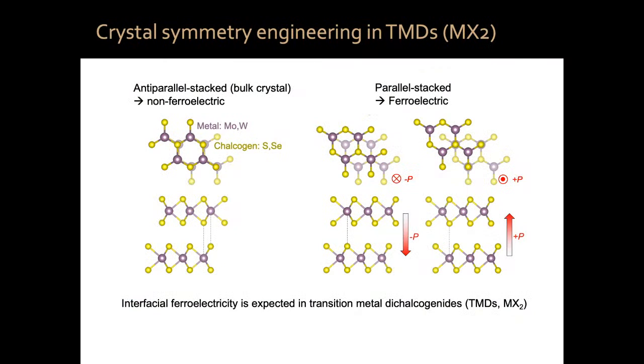only thing that we needed was to have this bipartite lattice. So this crystal symmetry engineering that we did in boron nitride, we can try to see if we can recreate it in any other bipartite lattice. So in particular, we did this with the transition metal dichalcogenides, which are also single unit cell semiconductors. They look from the top similar. You see this honeycomb lattice with alternating metal and chalcogen atoms.